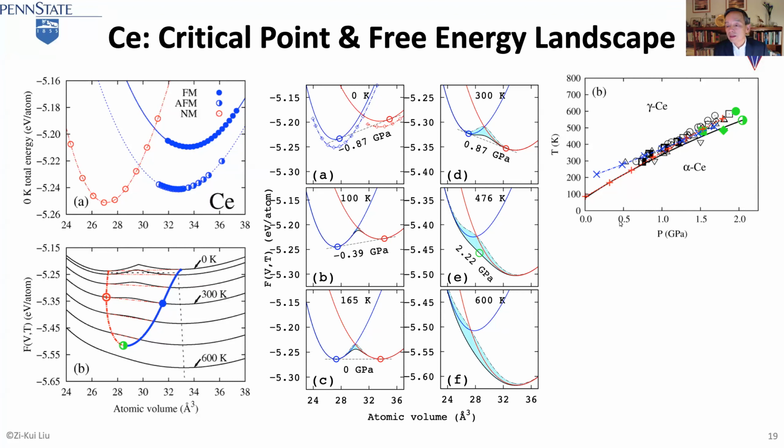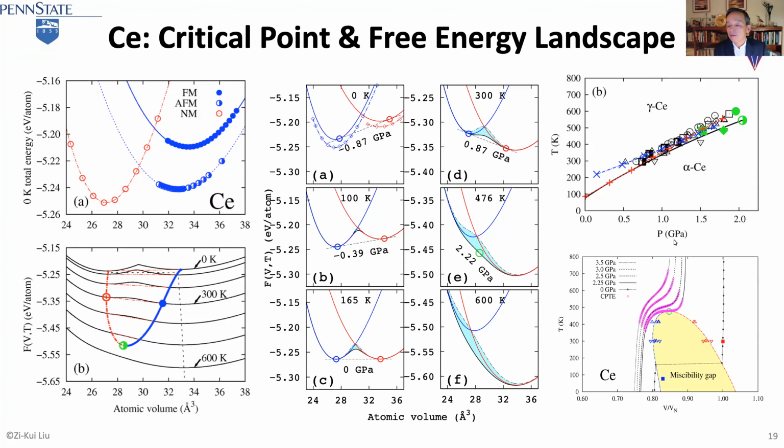Now we can change the pressure to its conjugate variable, volume. We get another diagram, the temperature-volume phase diagram. Now we see that the critical point becomes a maximum point here. When temperature is below this critical point, we have two-phase equilibrium. One of them has smaller volume and another larger volume. So this side is more ferromagnetic, and this side is less ferromagnetic. But all of them are mixtures of the 3 configurations. It's not a single one, until you go to 0 Kelvin.